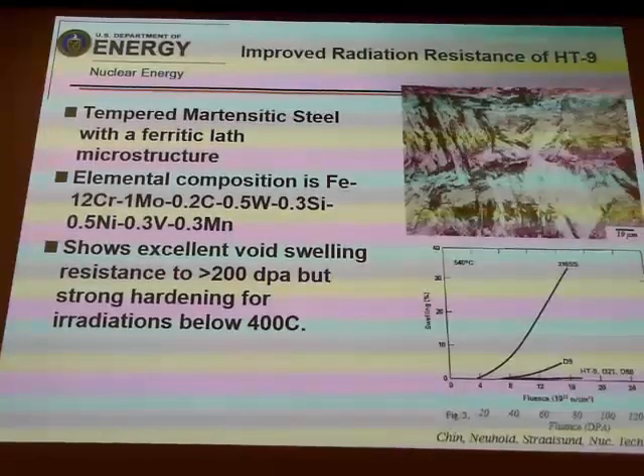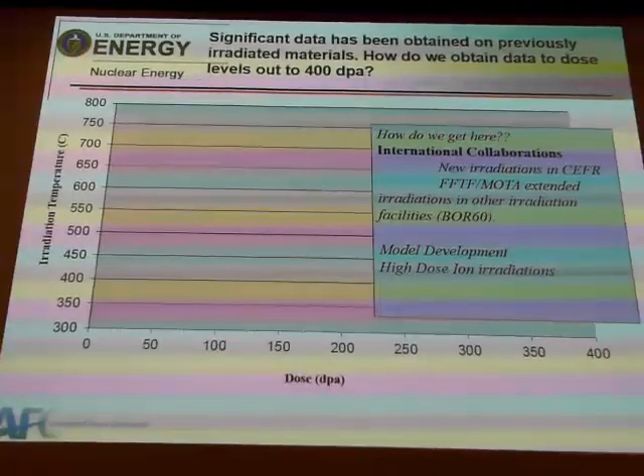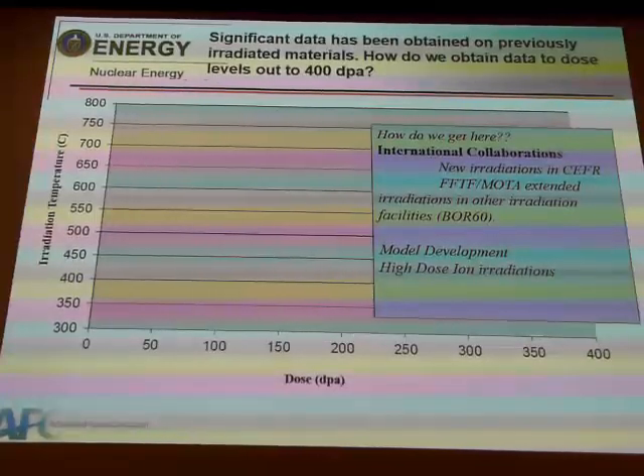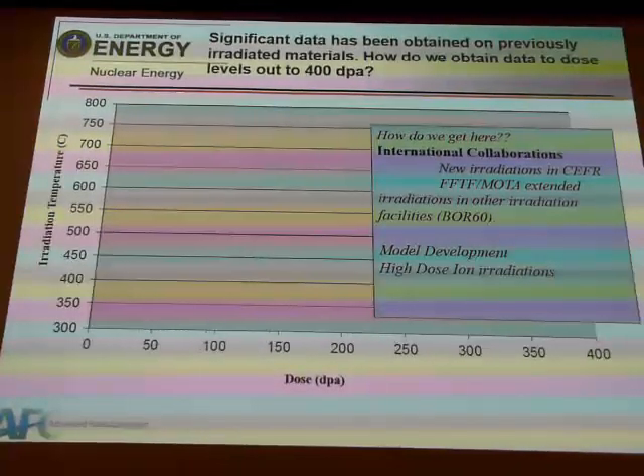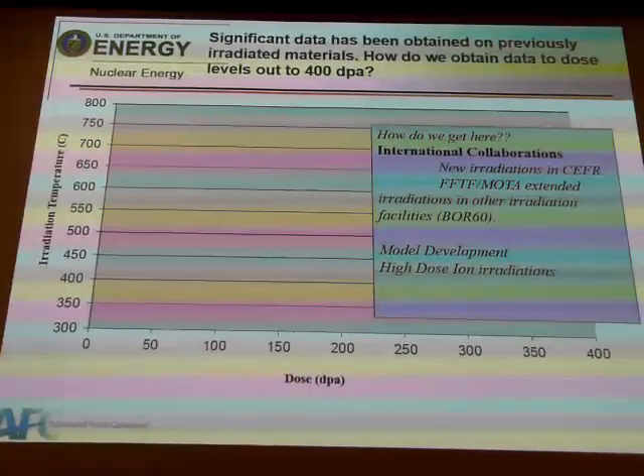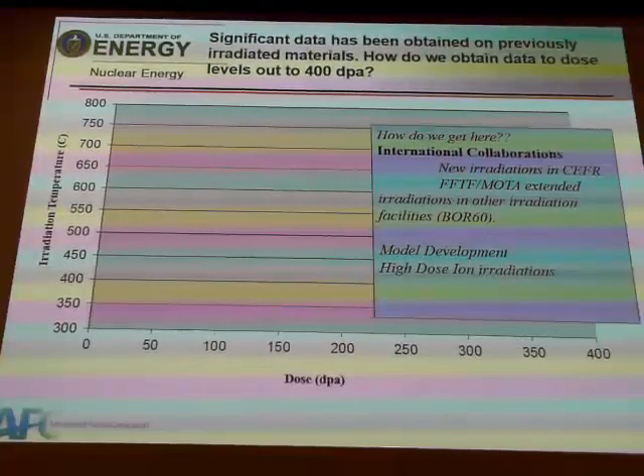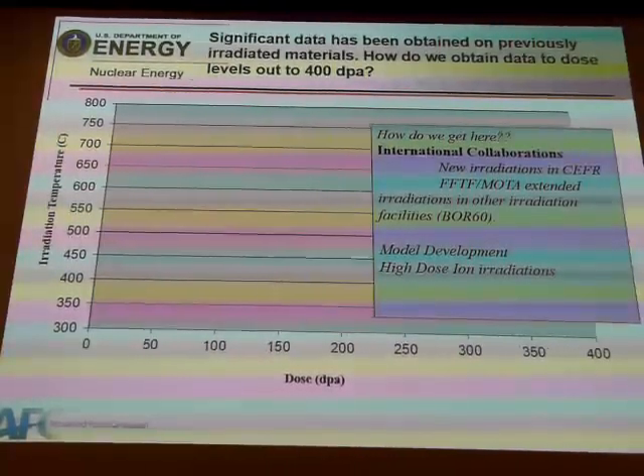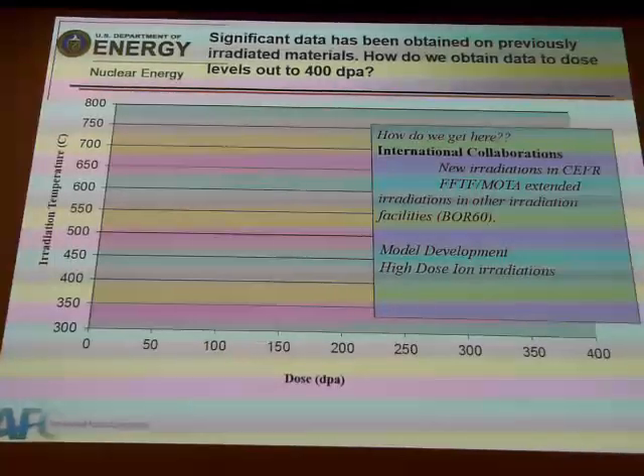And one of the things we're working on is how do you know when HT9 actually starts to swell, because there isn't very much high dose data way out here. So that's the question. How do you get very high dose data on materials? In a typical fast reactor, you can get in the core about 20 to 30 DPA a year. So if you want to test the material at 200 DPA, you've got to irradiate it for 10 years just in the reactor, not including the time it takes to take it out and do the PIE on the material. If you want to go to 400, you're going to almost 20 years, which is past the PhD generally, I hope.